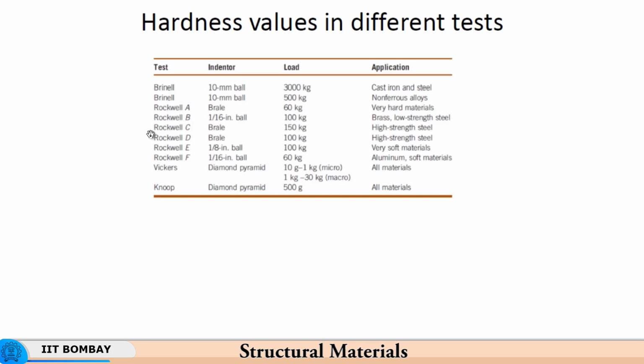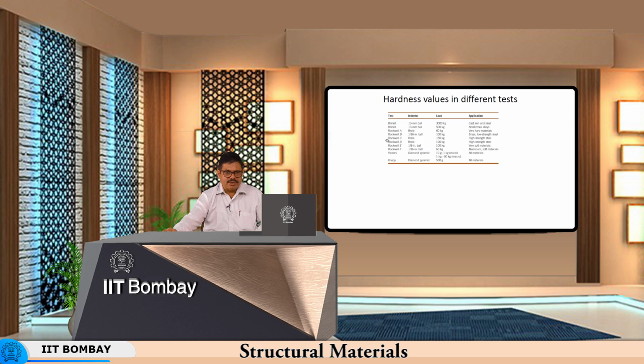For Rockwell A, B, C, D, E, F, different kinds of indenters are used and different kinds of loading conditions are used, and they correlate with the properties of the material, whether it is hard or soft. So, high strength steel would require a Brale indenter with a higher loading, but very soft materials would require a small steel ball which will be loaded to relatively small loads.